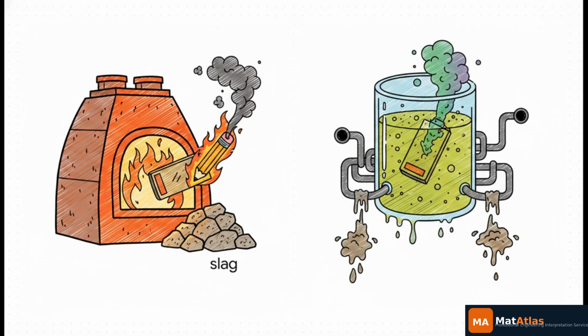On the other hand, you have hydrometallurgy. This relies on dissolving spent materials in strong mineral acids, like sulfuric acid. It generates immense liquid chemical waste, emits toxic gases, and requires a ridiculously complex series of chemical precipitations to separate out the cobalt, nickel, and manganese before you even get a chance to recover the lithium. Bottom line, both methods are inefficient and way too resource heavy.